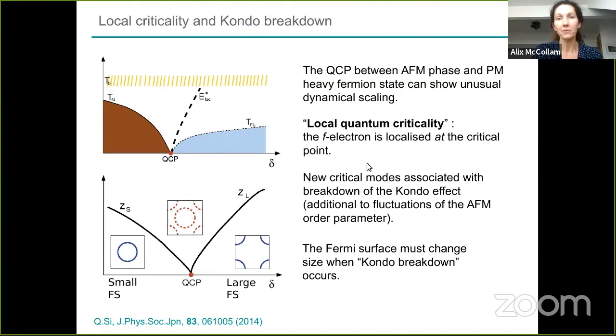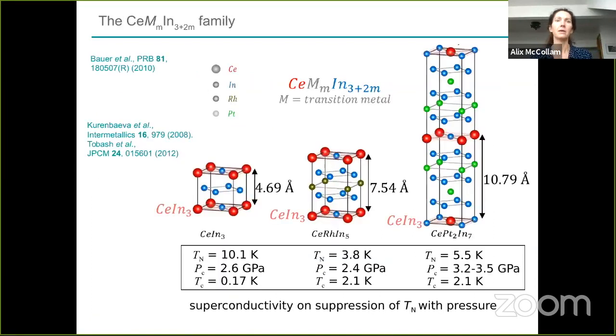The Fermi surface, to identify this, we should be able to measure the Fermi surface, and we should see a change in size. So you have a small Fermi surface on the ordered side and a large Fermi surface on the disordered side, or on the paramagnetic side.